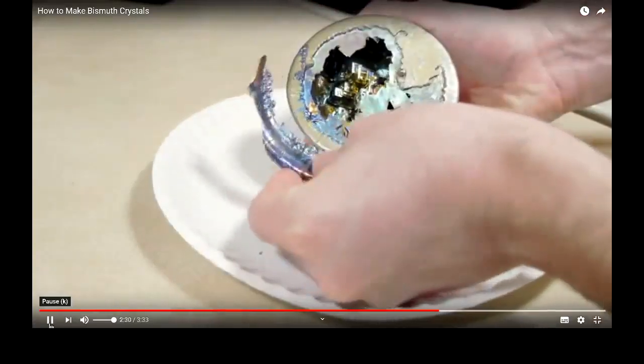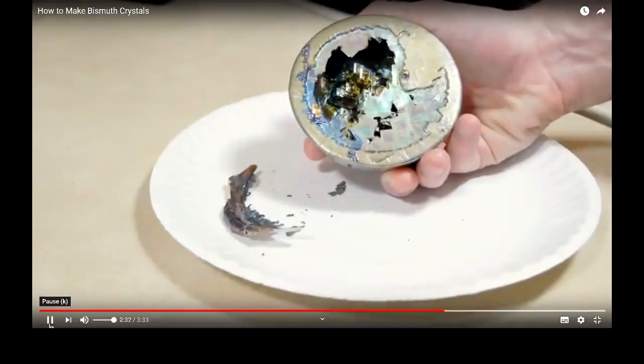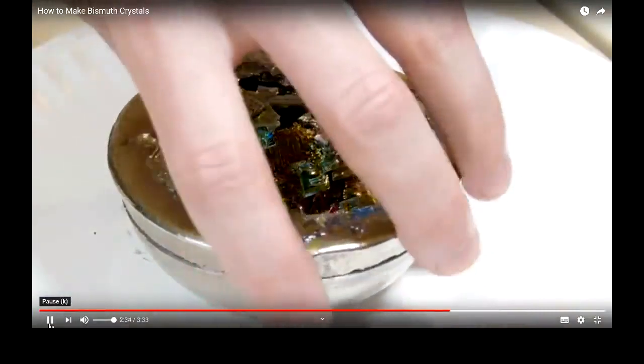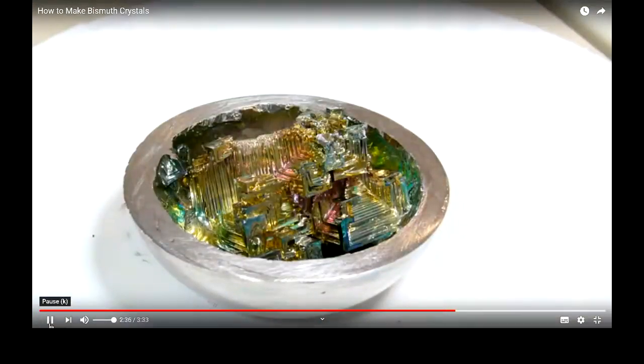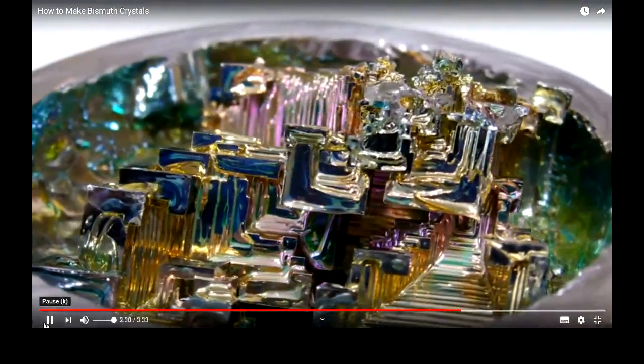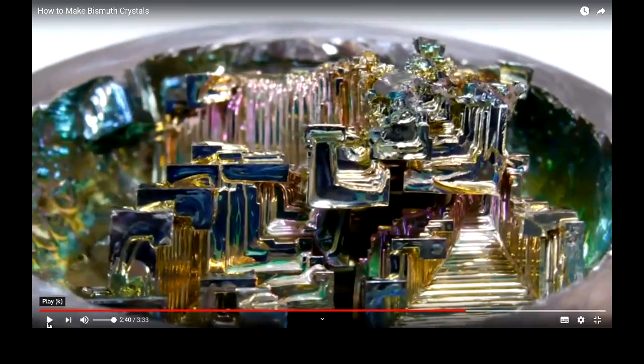The crystallization can be revealed further by cutting the top portion off entirely. I did this with a hacksaw. If you enjoyed this project, I'll just pull it up there. You'll also notice the ones that were grown from the surface and the ones that were grown from the base of the ceramic bowl, just how shapely they are. Okay, these have got 90-degree growth directions.